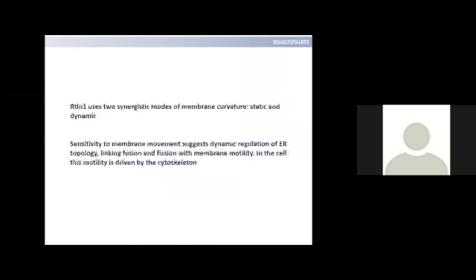So in conclusion, what we have observed is that reticulon 1 is using two synergistic modes of membrane curvature, static and dynamic. And the sensitivity to the membrane movement suggests that this dynamic regulation of the topology of the endoplasmic reticulum links fusion and fission with membrane motility. In the cell, this motility is driven by the cytoskeleton, and that's the mechanism that reticulon is using to promote fission of the ER.